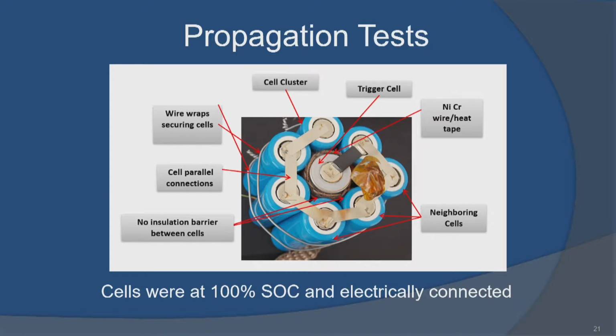Now, for safety. What we did was propagation tests. We're specifically attaching large format batteries. So, when you think of a big battery, you don't have one cell that's big. What you do is you have a lot of these 18650s like Jay showed, you string them together and there's many, many little players all in the large format battery. So not really if, but when one of them misbehaves, what does it do to its nearest neighbors? Well, in a conventional, very volatile, very flammable organic system, when one guy misbehaves, all of his neighbors join the party, and then you have a big fire and a big, big problem. What we do is we make sure that it does not propagate. That means when, not if, but when one battery misbehaves, all the ones that just happen to be right next to them do not play the game.